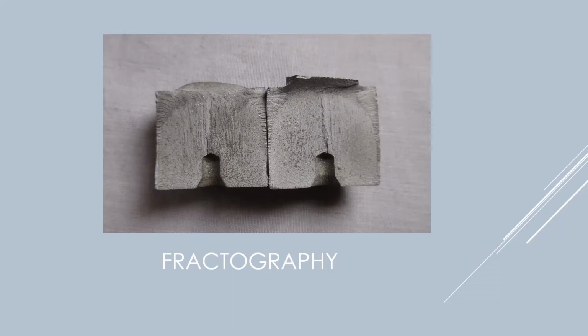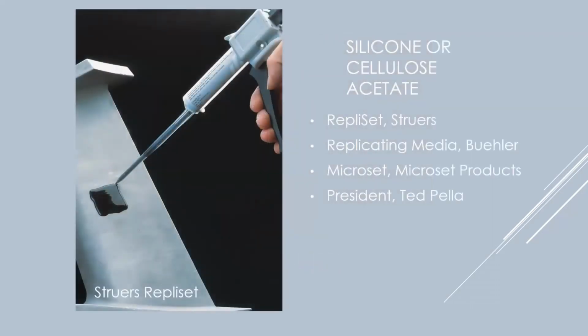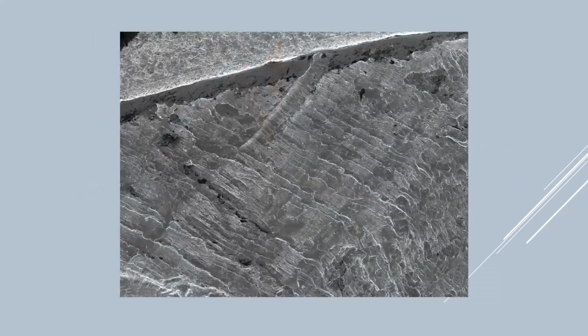And so you have to take a replica of the fracture. Other times they're going to do the repair immediately, in which case they don't want you to start cutting up a fracture because they're going to weld over it anyway. So being able to take an image of the fracture is certainly useful. And you remember we talked about how we can use either cellulose acetate or silicone rubber to replicate that fracture. And this is a silicone rubber replica of a fatigue failure.